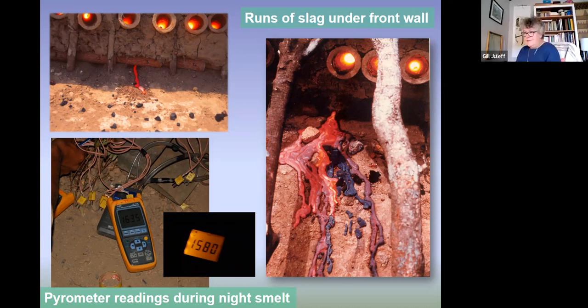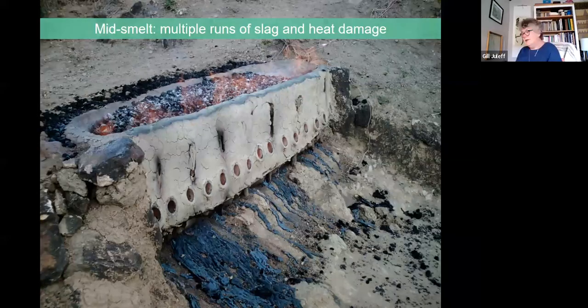This is how that structure looks well into the smelt. You can see we've had a lot of slag coming out of the bottom. The wooden poles that we put in to help the front walls stand up have all been burnt out. The ends, the corners of the furnace are burning down quite heavily. All of the smelts we've done, or almost all of them, went into the night. The reason for that was it enabled us to see the flame and the gases on the top of the furnace more clearly. And also it is a very dramatic experience.